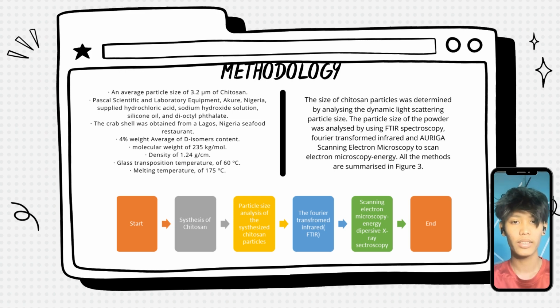Assalamualaikum warahmatullahi wabarakatuh. Next, I will proceed to our methodology. In our study, we use materials with an average Chitosan particle size of 3.2 micrometers. We use hydrochloric acid, sodium hydroxide solution, silicone oil, and dioctyl phthalate.